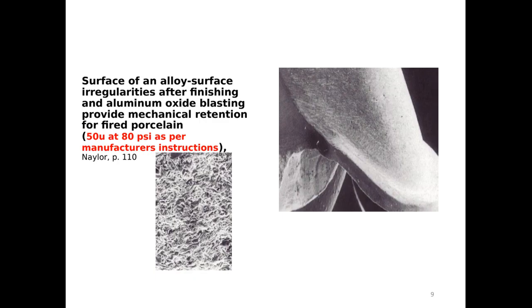So this is how the surface of an alloy, with irregularities after finishing with the burrs and then applying the sandblasting with aluminum oxide, looks like. And this is what creates the mechanical retention for applying the porcelain. So we see in the picture here how under the microscope the surface of the metal is rough. And that is what creates a good bonding for the porcelain when we are ready to apply the porcelain.